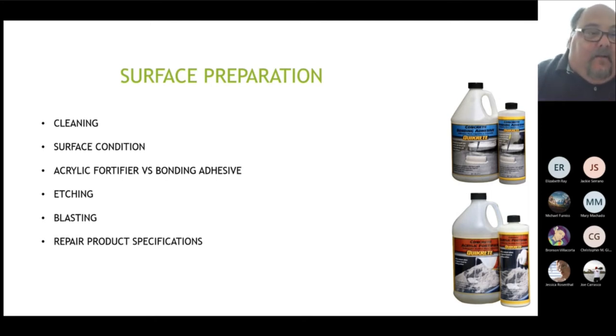There are two different products that help bond existing to the new: concrete acrylic fortifier, which is on the bottom, and concrete bonding adhesive. The concrete bonding adhesive at the top is a primer, if you will. What it does is it goes over the surface, it covers the pores, it soaks into the pores, so that way there's not excessive moisture loss. And then it also acts like a contact cement. So when you put the new product on top of the old, it re-emulsifies and gets really sticky, and that helps make a chemical bond as well.